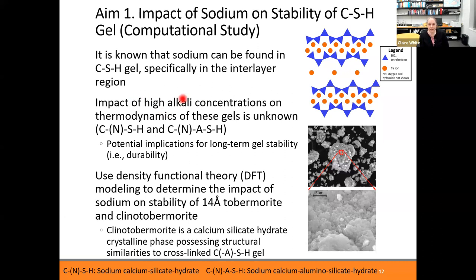So the impact of high sodium concentrations is not well known. And so what we've done here is use density functional theory, computational chemistry, to determine the impact of sodium on some model phases. And as you're probably aware, with computational chemistry, there's a limitation to what size systems you can study. Larger system sizes, you tend to use force field-based techniques. Here, we're using density functional theory because we want to get accurate information on the energetics of the system. But we have to compromise on the system size.